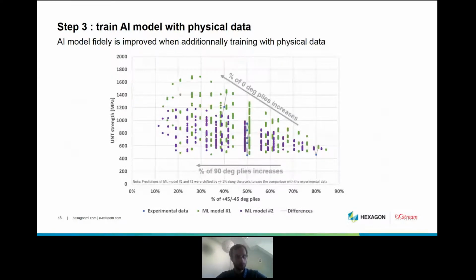So now that we have an AI model which has been trained on the simulation data, we will train it on top with the physical data. What happens here is that the AI model fidelity is improved when we train additionally with physical data, because we are able to capture what is happening exactly in the real world. And in this case, we took a kind of tricky combination for the simulation models, which is the ply bunching effect, which was not present in the simulation model that was used. And what we see is that once we include the experimental data in the training of the AI model, which is here in purple, it becomes much closer to the experimental data.